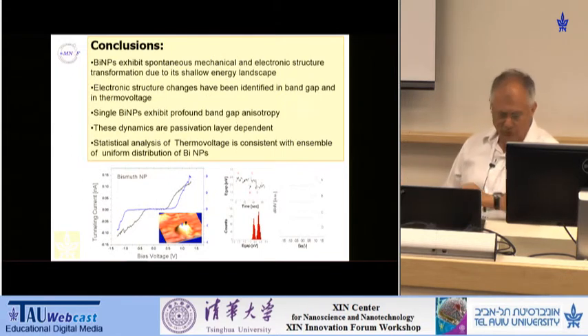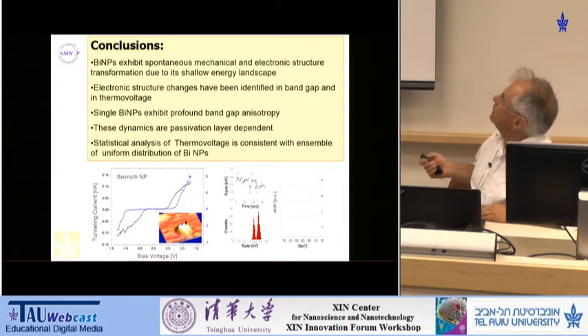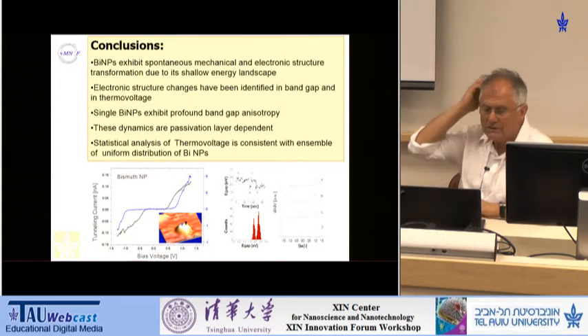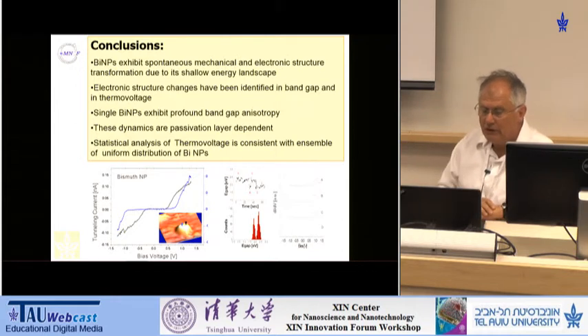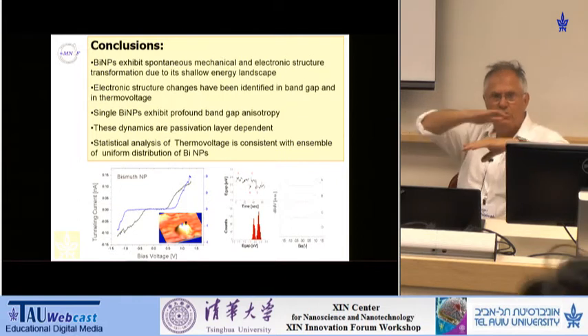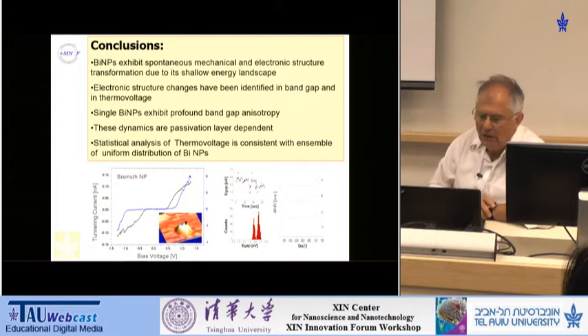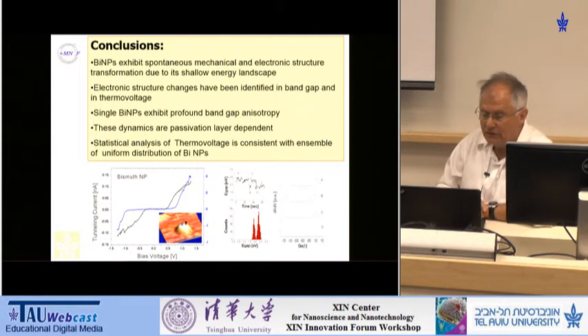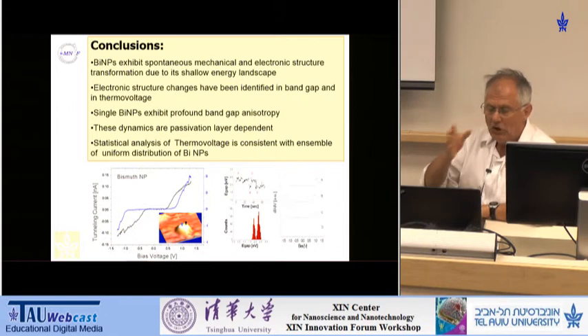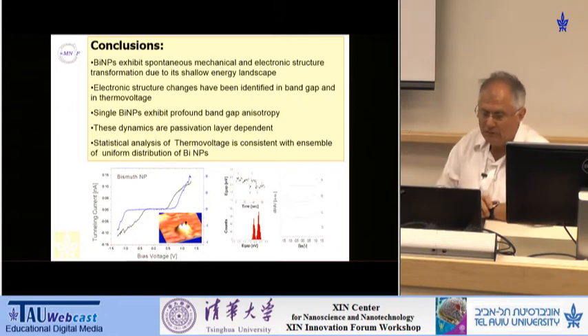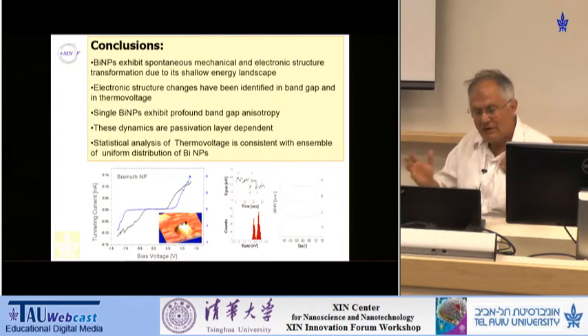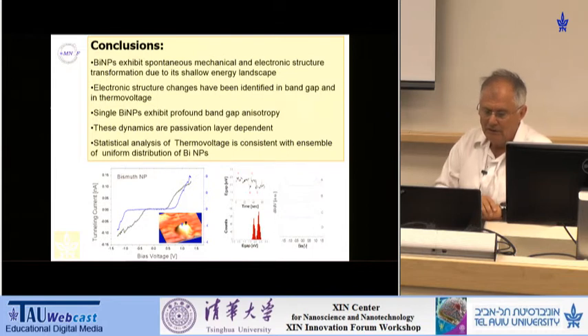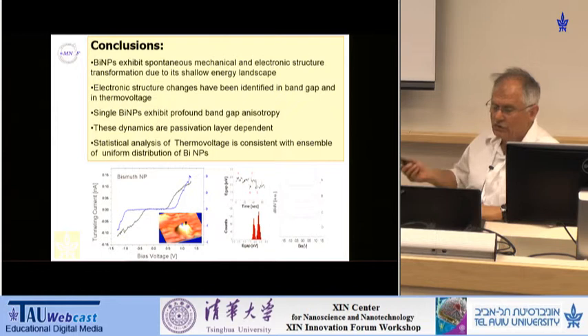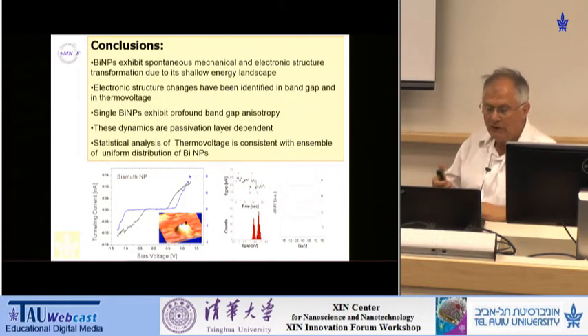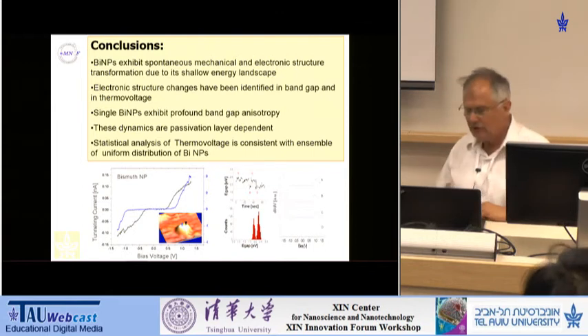So that's the end of my story with the conclusions that bismuth nanoparticles exhibit mechanical and electronic structure transformation due to its shallow energy landscape. Namely, it's relatively easy to go between one form and another. And the electronic structure changes have been identified in the band gap and in thermovoltage. And that within a single nanoparticle, you can measure profound band gap anisotropy. And that this dynamics can, to some extent, be controlled by passivation layer. And that statistical analysis of thermovoltage is consistent with a complete ensemble of uniformly distributed bismuth nanoparticles. Thank you very much.